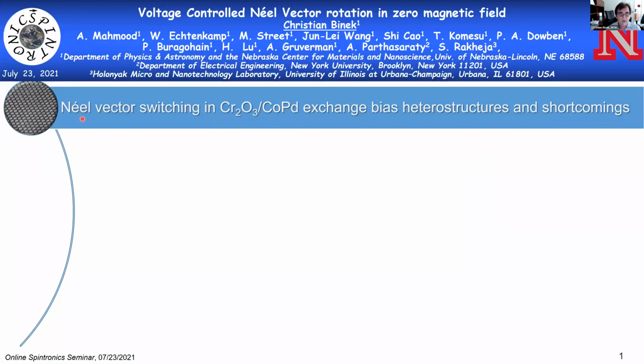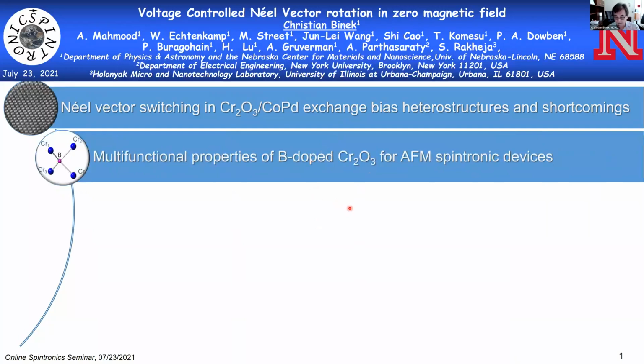So it all started out some longer time ago with the attempt to achieve Néel vector switching in exchange bias heterostructures, where the voltage active component of this exchange bias system was chromium oxide, a magnetoelectric antiferromagnet, an archetypical magnetoelectric material. And I will talk about what we did in these systems, what we achieved, but then also what the shortcomings of this approach are. One of them was right from the start that the Néel temperature of this material for applications in CMOS environment is low.